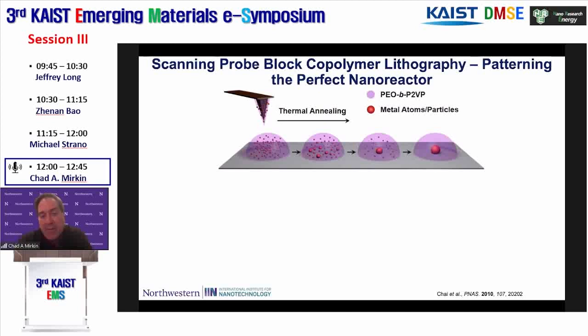Okay, so how do we think about making Megalibraries? Well, we have to develop a whole new way of thinking about chemistry. So we'd like to be able to control chemistry locally on a substrate with nanometer precision. And to do that, we employ the concept of what we call nanoreactors. We basically take polymers, in this case polyethylene oxide poly-2-vinyl pyridine, load them up with metal salts, put them on tips, either a dip pen tip or a polymer pen tip, as you're going to see. Deposit the tip on a hydrophobic substrate. These are hydrophilic materials, so you end up getting a droplet that beads up onto the surface. That defines what we call a nanoreactor.